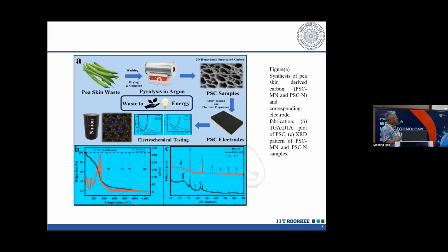Then this carbon material has to be converted into a slurry and pasted onto the sheet of aluminum foil, and then it is dried, and then this is inserted into the cell device, and then the electrochemical charging and discharging behavior is studied. Before that, the material was tested with thermal analysis by DTA and TGA methods to find out the calcination temperature and other such things. And then XRD analysis has been done.